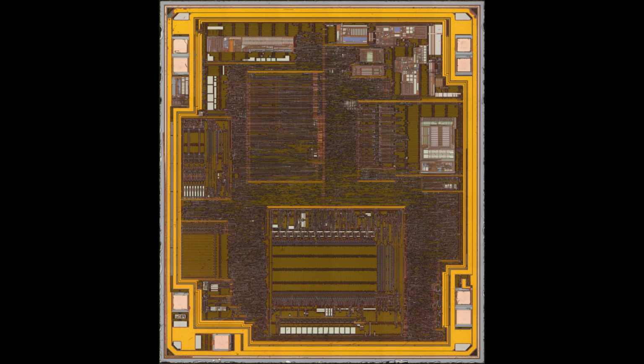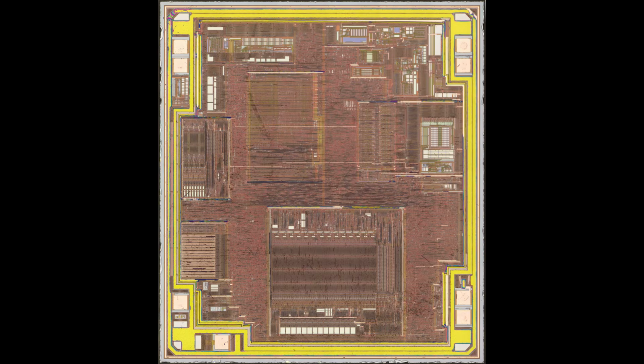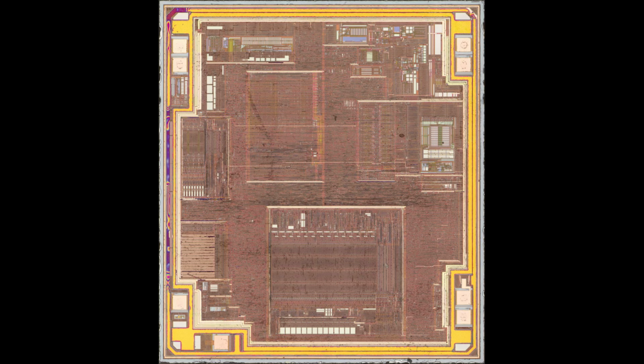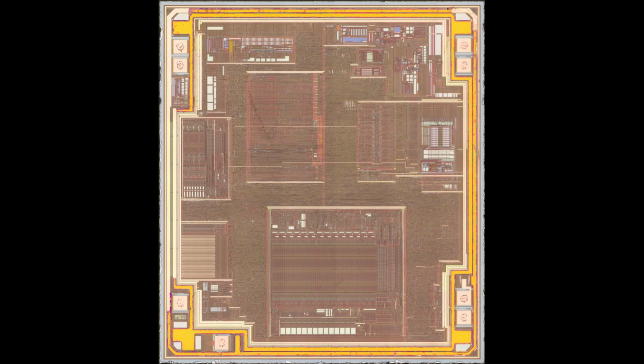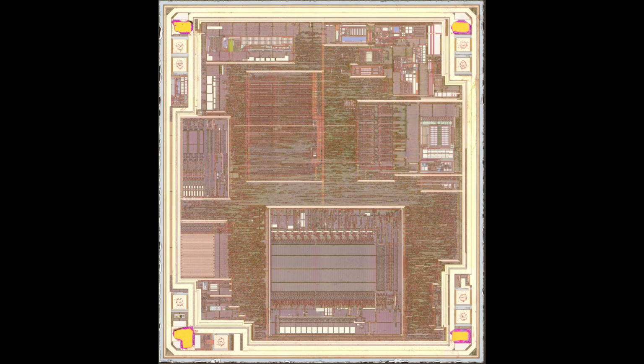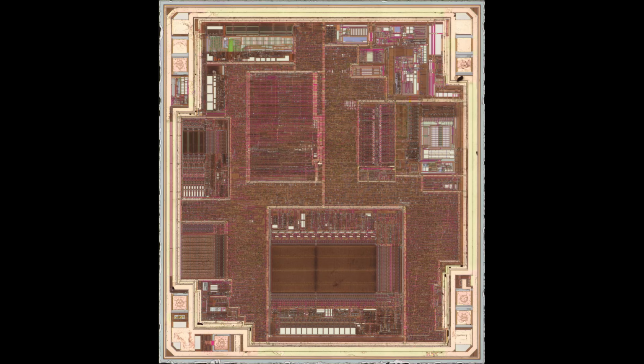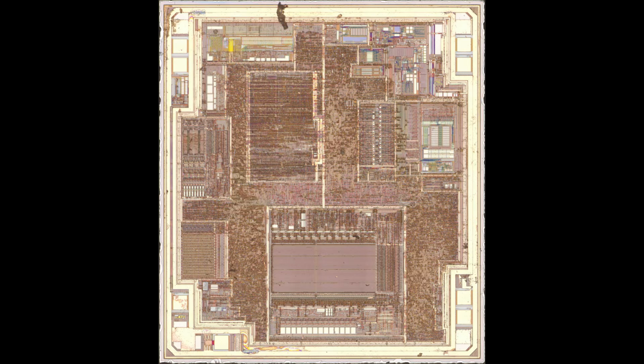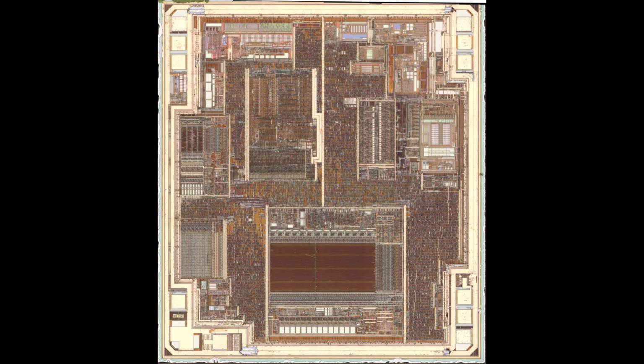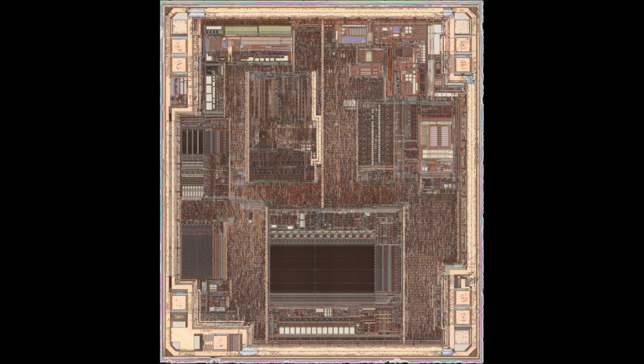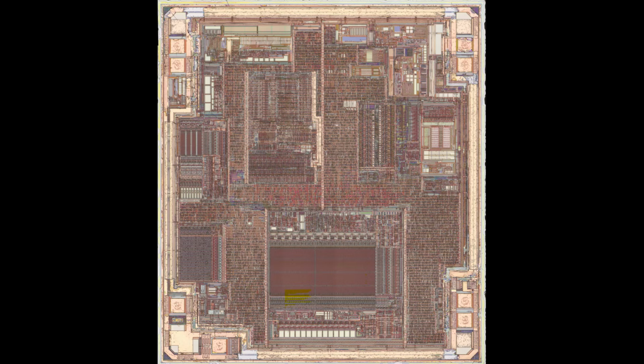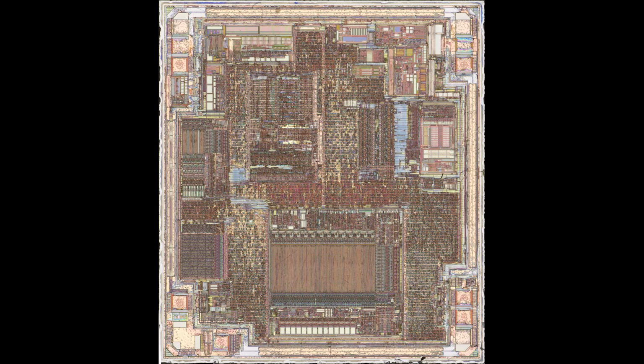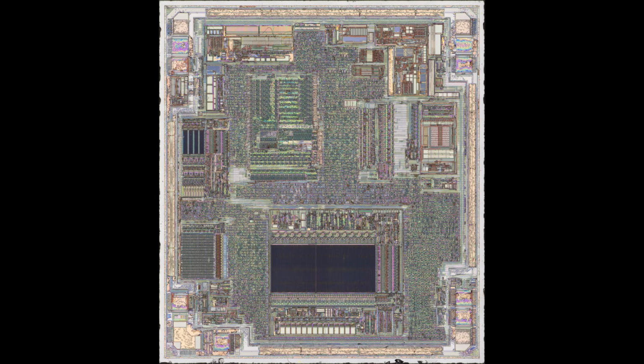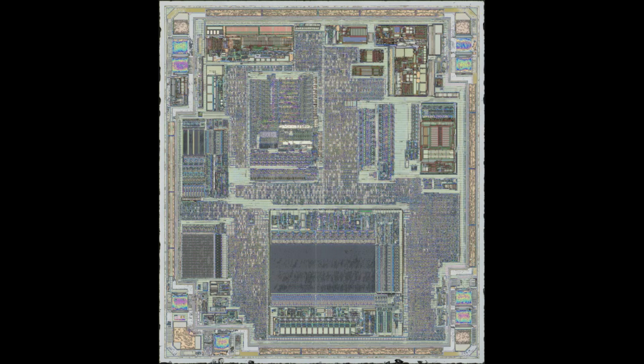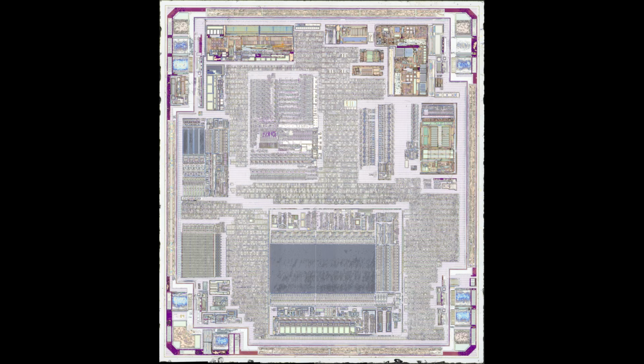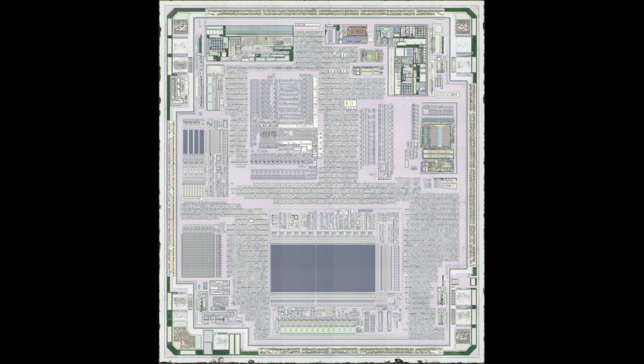Over the course of about 2 weeks, I did a total of 27 etch cycles. The device was imaged 66 times at 20x and/or 100x magnification, sometimes after cleaning steps as well as etch steps. The total data set acquired from all of this was 203.5 gigabytes, just under 370,000 photos. And in the end, we have the entire device imaged at full transistor level resolution on every layer. We can see every wire, every via, every conductor, and also some interesting tidbits like how the analog areas have higher glass density and lower metal density, so they etch slower.